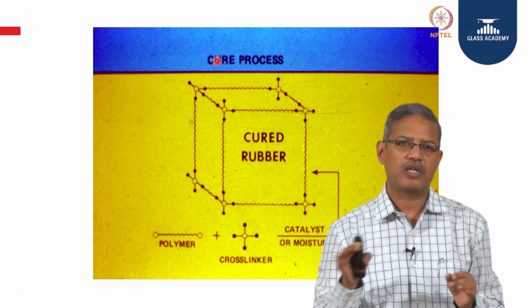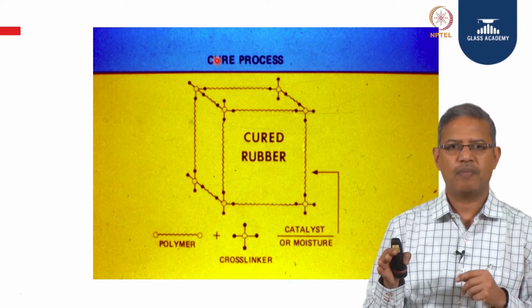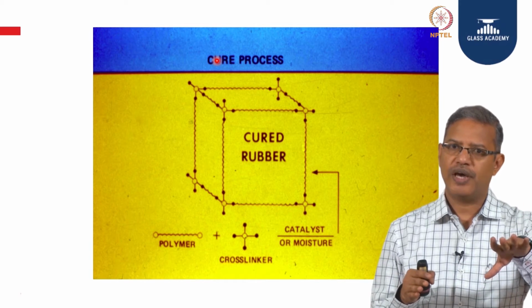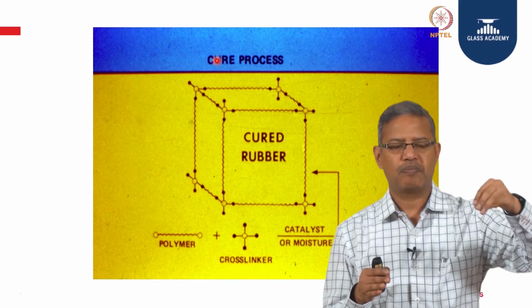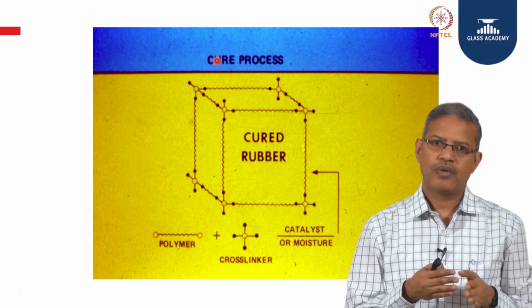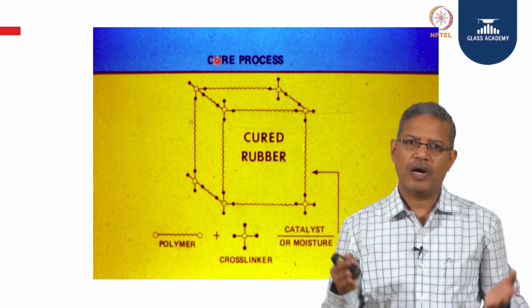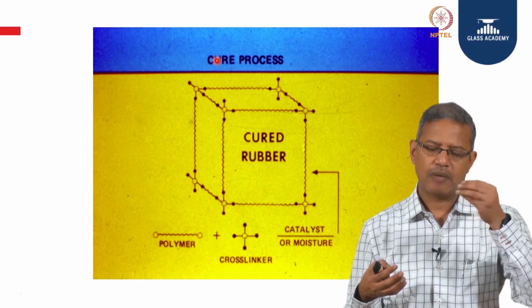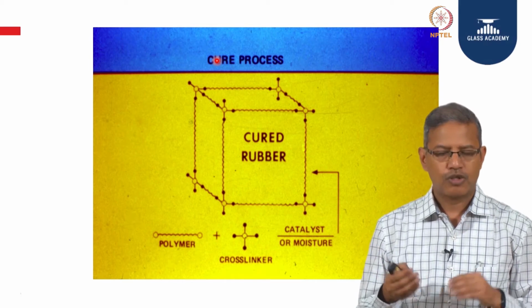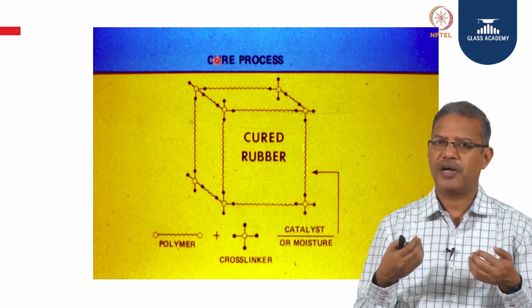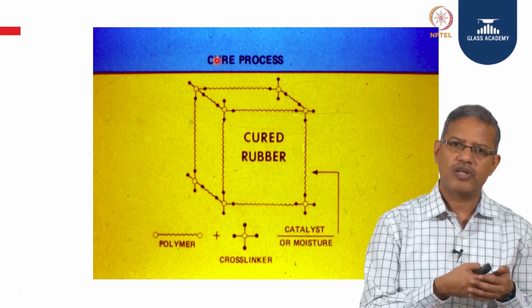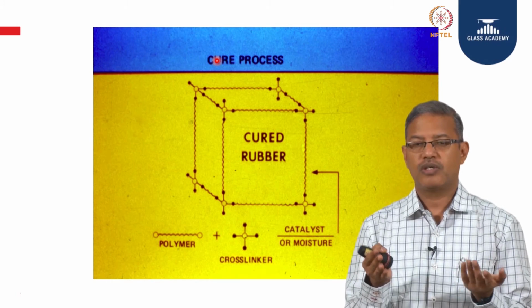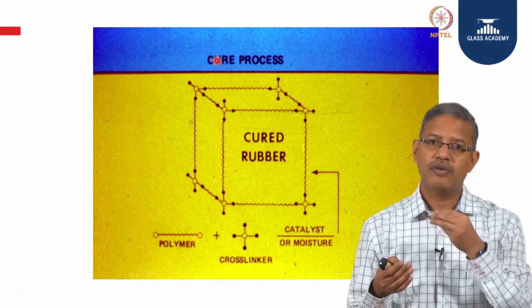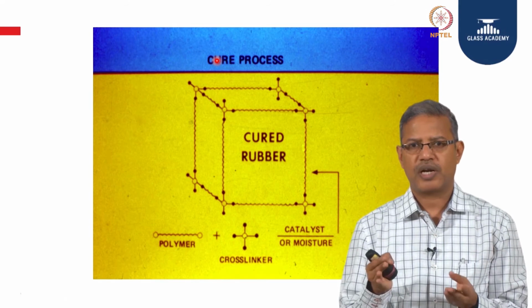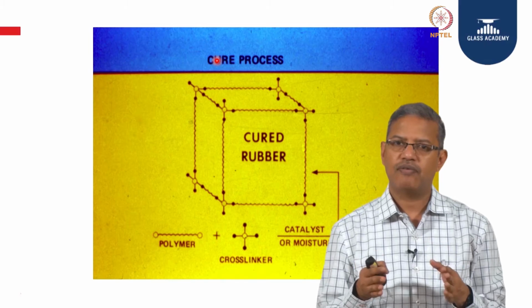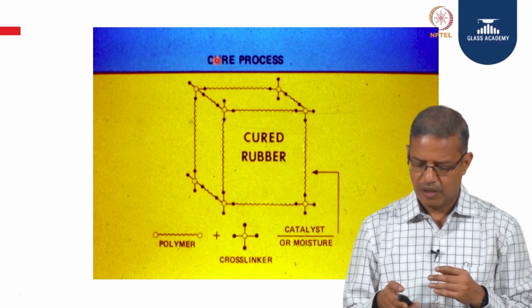So, all the joints we make using silicone for any of the applications should have at least one side exposed to the air. If it is one part, it becomes a process where the moisture can enter through, cure, and the byproduct is released. If it is a two part, there is a reaction which happens within itself and the byproduct is released through the exposed side. So, you cannot make a joint which is completely confined into a space, apply silicone and then pack it completely. The silicone will never cure. It will not fully cure to its strength and it will not give you the desired properties. This is an important criterion to keep in mind, that we need to have a joint which is open on at least one side, exposed to the air.